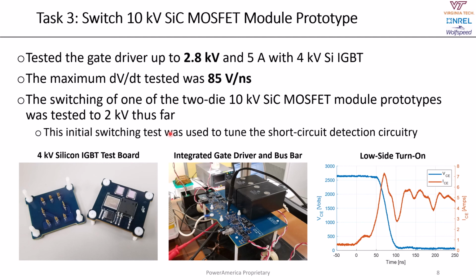We're also working on refining the gate driver circuitry. Thus far, we've tested the gate driver with a 4 kV silicon IGBT up to 2.8 kilovolt with a maximum dV/dt of 85 volts per nanosecond. We've also done some switching evaluation of this gate driver with a prototype 2-die 10 kV silicon carbide MOSFET module up to 2 kilovolt, and that was used to help tune the short circuit detection circuitry.